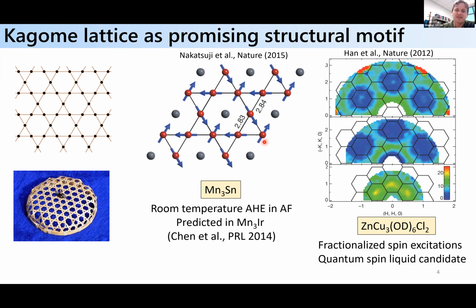Also there are the real space spin textures that you can realize by decorating the lattice, if for instance the system orders, in materials like manganese 3 tin, where you can realize effects such as room temperature anomalous Hall effects, and other interesting spin textures, for instance, on a magnetic lattice that's ordered, but with non-collinear spin textures across the kagome lattice.